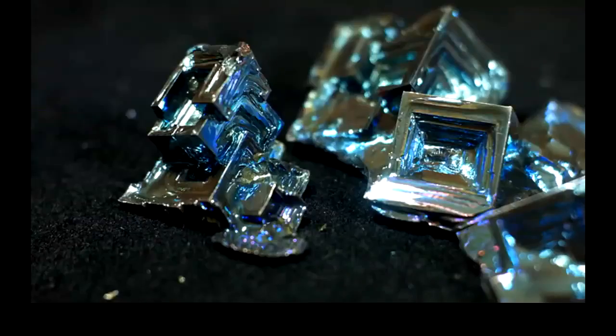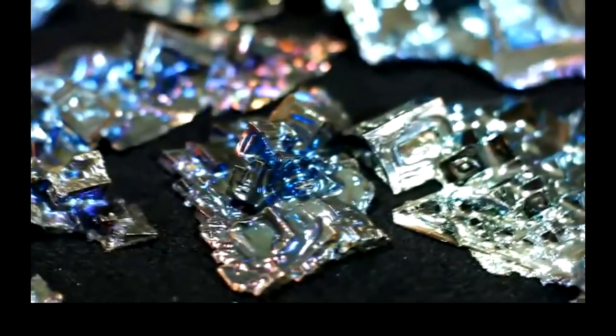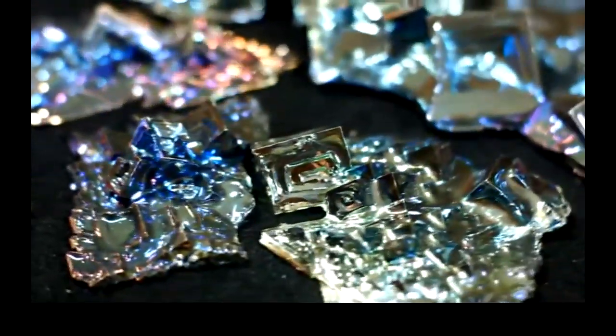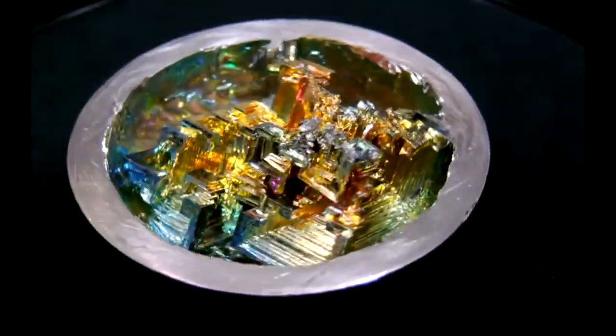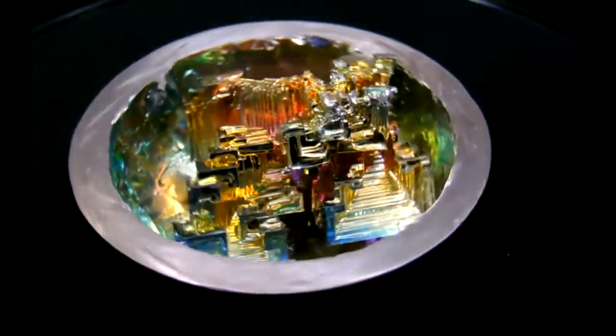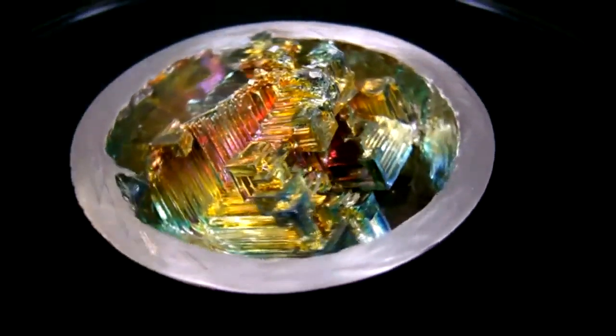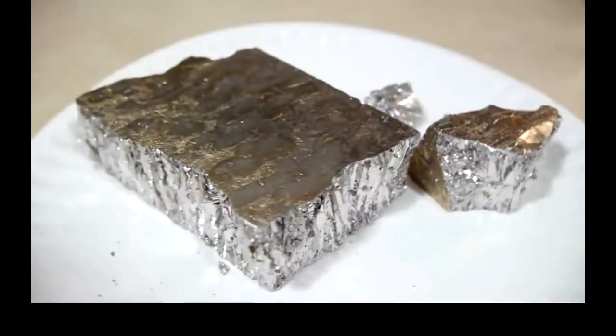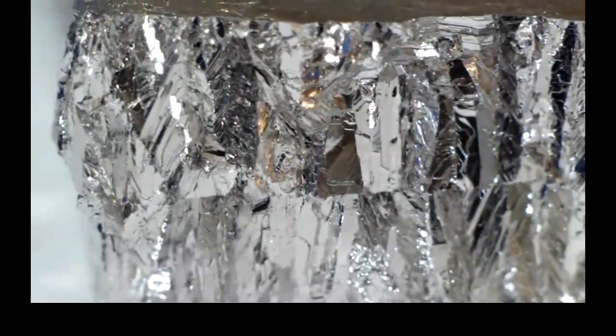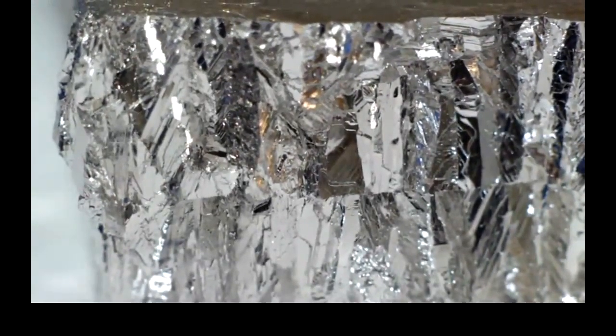Bismuth has a melting point of 520 degrees Fahrenheit, which for a metal is very low. It's still more than hot enough to cause burns, so for this project, safety goggles and leather gloves are essential. This is 5 pounds of bismuth metal in the form it's usually sold. The first step in the process will be to melt this down.